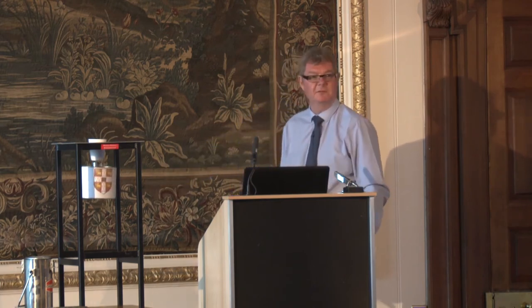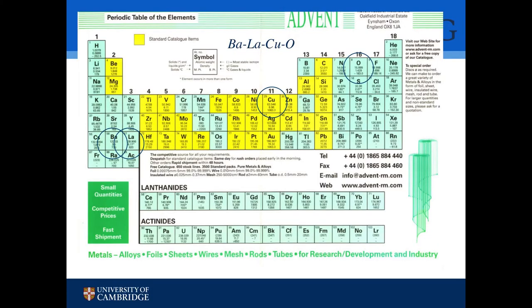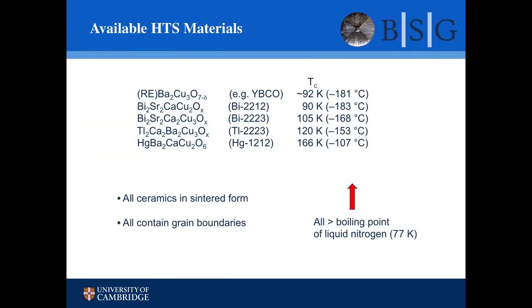But it reports a barium lanthanum copper oxide system that shows a large change in resistivity at around about 36 Kelvin. And it turned out, if you look at the periodic table, that if you take lanthanum, barium, copper and oxygen, and you just move from lanthanum to yttrium, so it's the same group, you just move up one, that's all you do, you find you have a material with a TC of 92 Kelvin. It's extraordinary. Bednorz and Müller won the Nobel Prize in 1987 for this work.